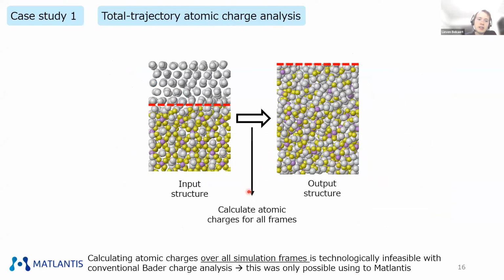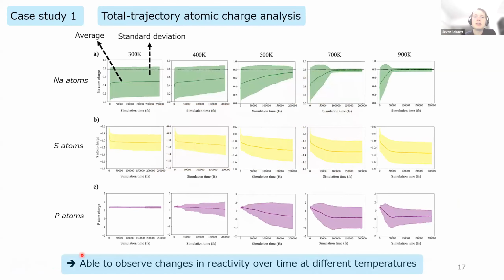But as I mentioned, it's not only the input structure and the output structure, which contain very valuable information. It's also what happens in between these two. And so that's, once again, something which Matlantis is really good at. It can calculate the atomic charges over all simulation frames. So for our simulations, it was 200,000 frames, 200,000 femtoseconds. And we're able to get those results in about a minute. So it really shows how powerful Matlantis is.